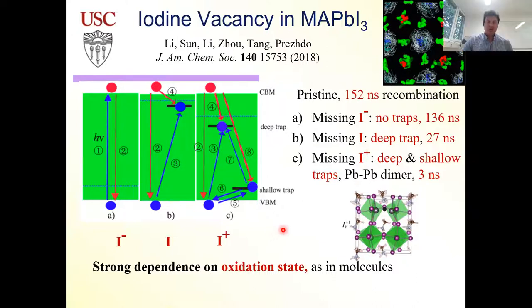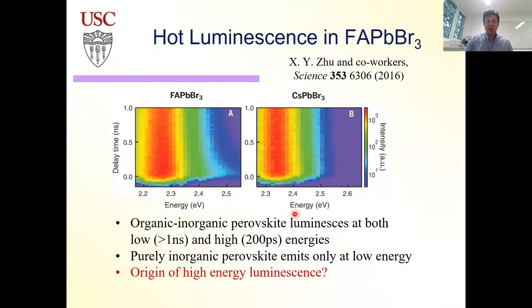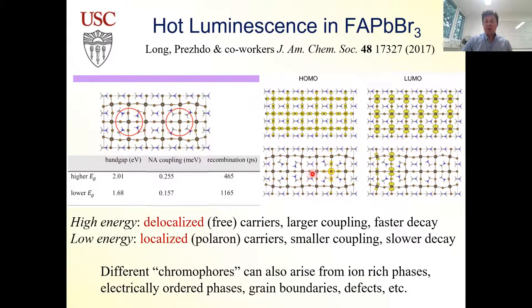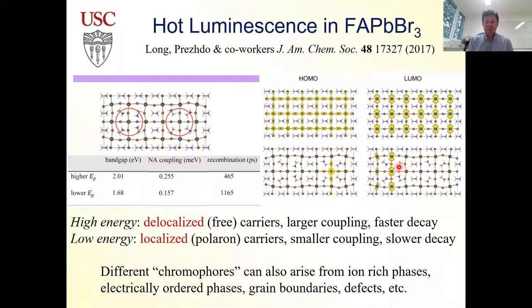Weitao asks about comparison with surface hopping. What we do is a form of surface hopping. The main approximation is the classical path approximation: we assume thermal fluctuations are much larger than geometry changes between electronic states. In perovskites you have the organic molecule rotating and the inorganic lattice fluctuating a lot — you even see polaron formation, which we can model in ground-state DFT. We still do either FSSH or our own hopping methods to reach Boltzmann equilibrium, since propagating time-dependent Schrödinger equations alone cannot dissipate energy to heat — so it's surface hopping adapted for nanoscale materials.